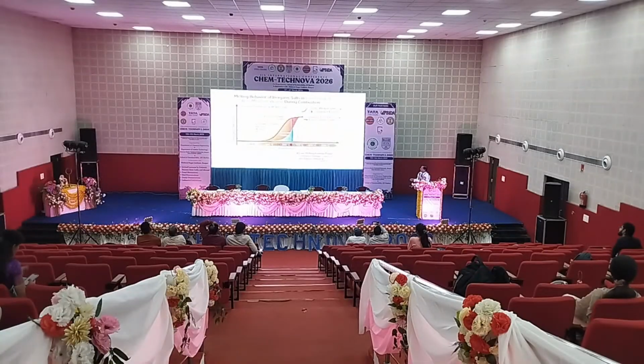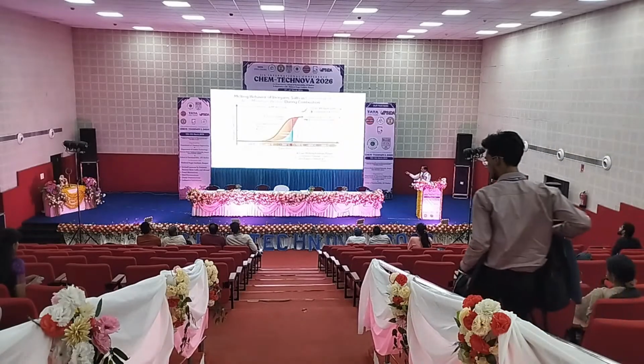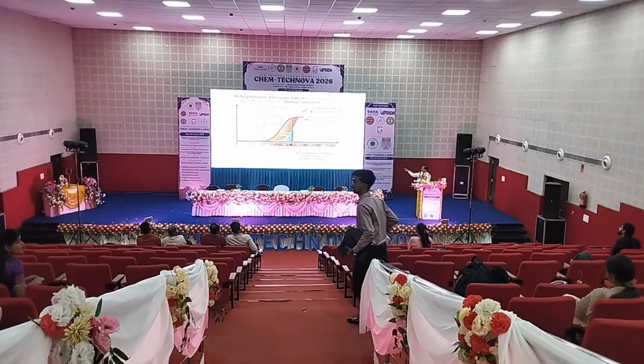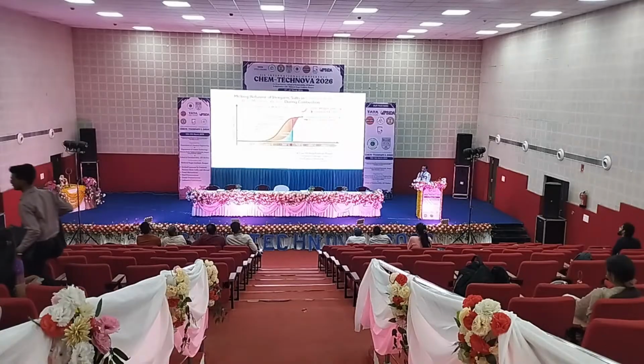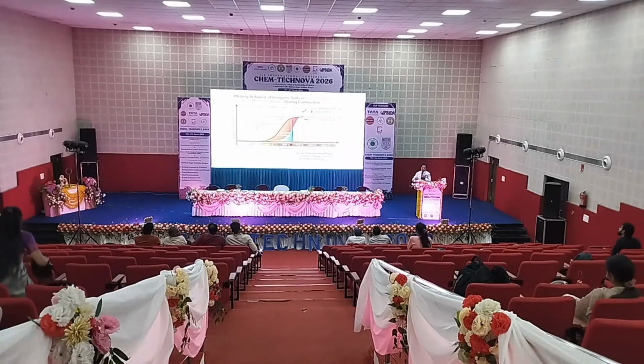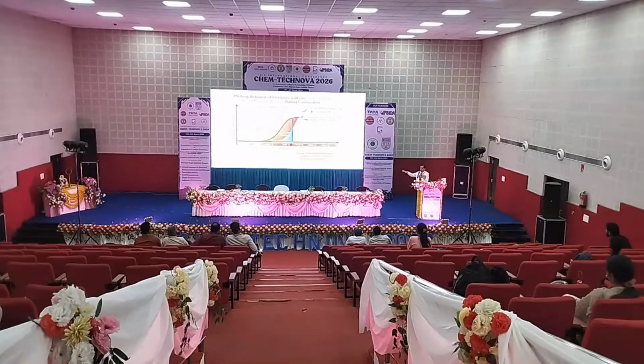So this graph shows the melting behavior of the inorganic salts in the concentrated molasses vinasse during combustion, with temperature from 50 degrees centigrade to almost 900 degrees centigrade. The most critical zone is between 550 to 650 degrees centigrade, where eutectic melting is taking place. So the modern boilers maintain the temperature in the convection module between 550 to 650 degrees centigrade, so that as soon as the eutectics are formed, they get deposited in that region. And whatever fuel comes out is like a clean fuel, which could be used for generation of steam.